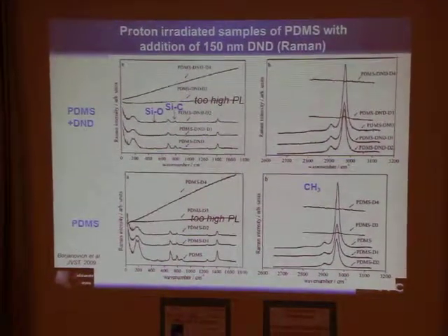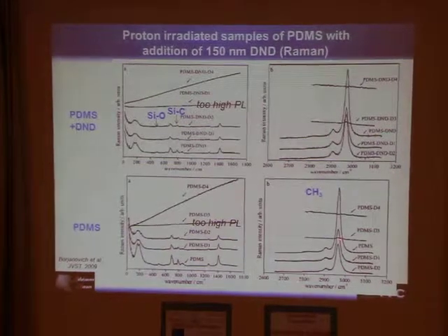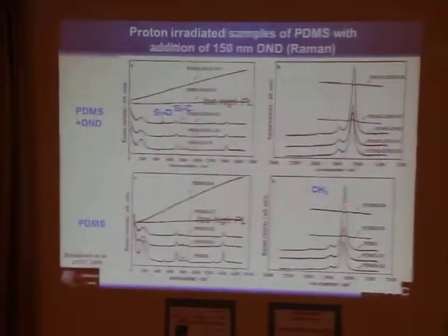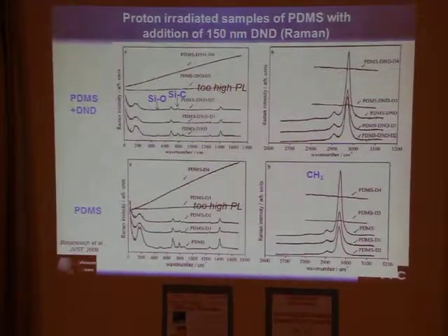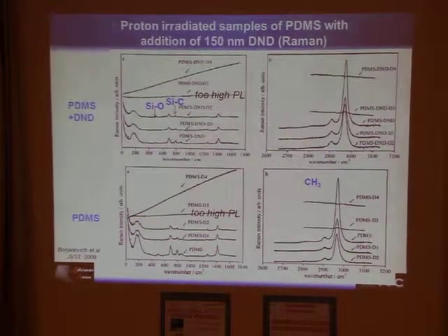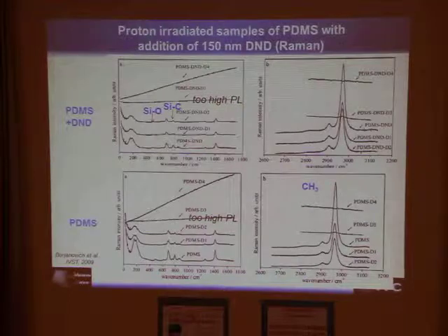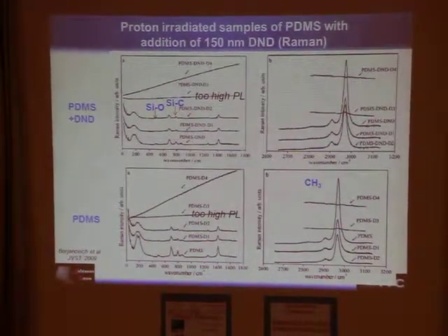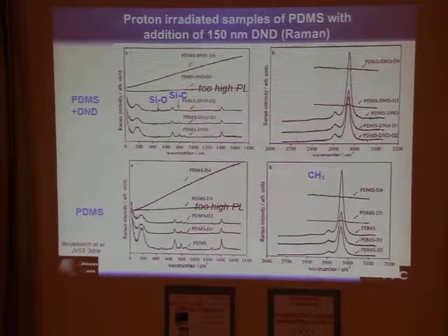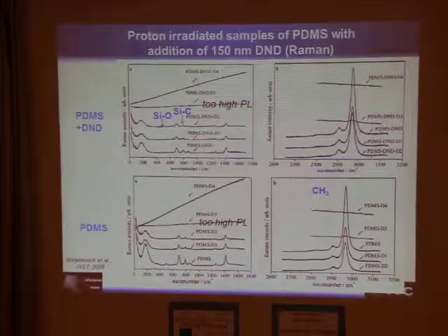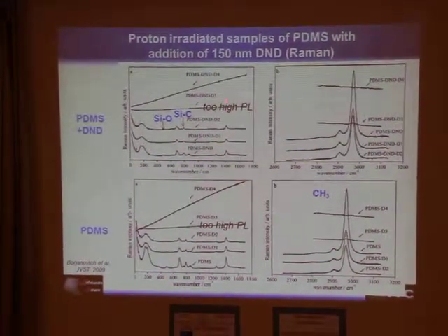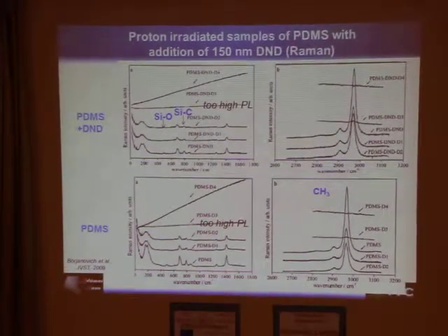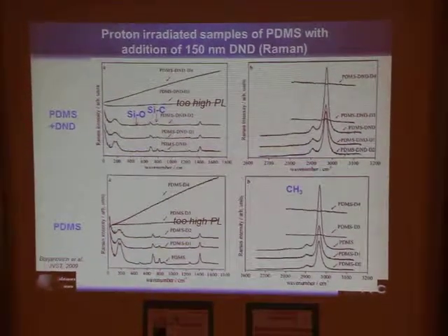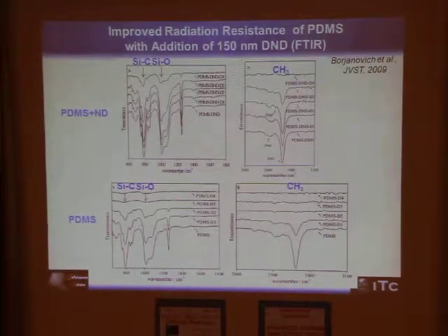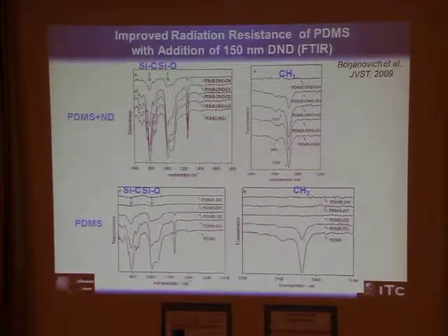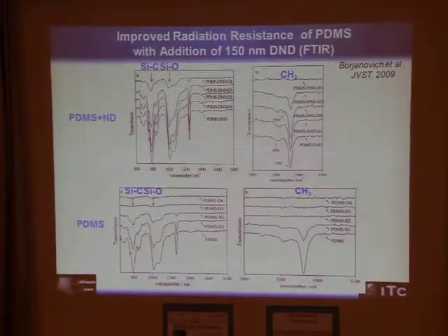So let us also look at the PDMS CH3 bond. Its initial peak, and at D1 and D2 irradiation doses, you can see a decrease of the peak intensity. What happens if PDMS contains nanodiamond? In general, you can see in this representation a similar decrease of the characteristic peaks, and again the high PL prevents us from further analysis at the more interesting high doses. So what was used was FTIR spectra, which provided us more detailed information for all irradiation dose ranges.